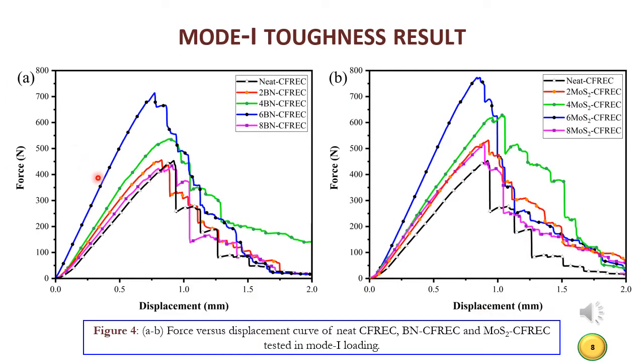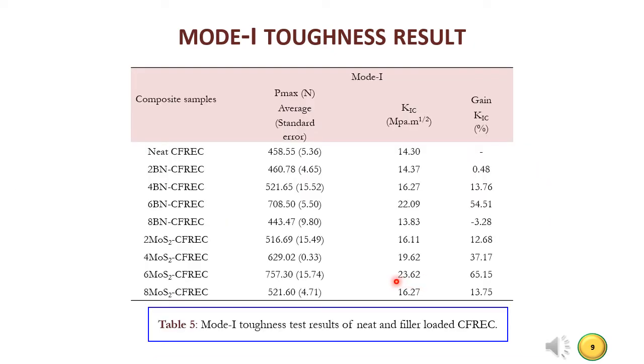Figure 4a shows force versus displacement response of hBN filled CFREC and 4b of MoS2 filled CFREC in mode 1 test. The highest slope is noticed for 6BN CFREC. The stiffness of filler loaded CFREC is higher compared to neat composite. The increased stiffness and toughness are attributed to uniformly dispersed high modulus filler in the matrix. Interestingly, a stick slip pattern is detected beyond peak load, attributed to unstable crack propagation in the composite. The highest KIC of 23.62 MPa square root meter is obtained for 6 MoS2 CFREC. KIC improvement is due to better filler interaction with epoxy, which arrests crack propagation smoothly.